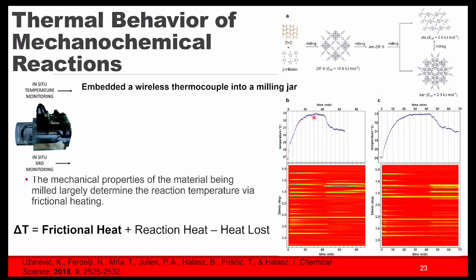And this is due to frictional heating, right? You have this mill, you've got balls inside of it, everything's rubbing together, you're getting a bunch of friction, so the temperature goes up. And eventually this friction basically equilibrates with the heat loss to the environment. You're starting at room temperature at 25 degrees C. Eventually, the jar equilibrates at about 32, 33. So frictional heat is going to go with the heat loss.